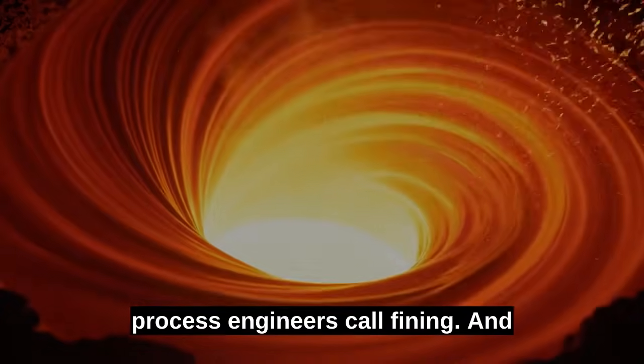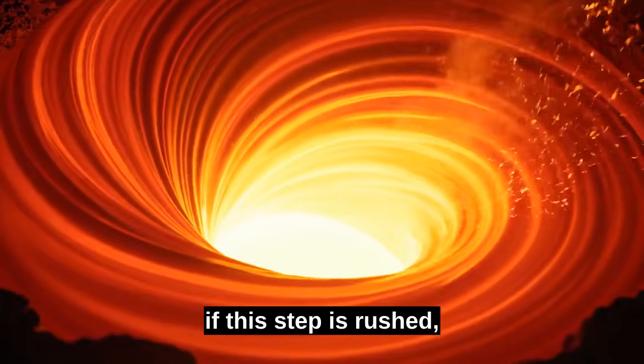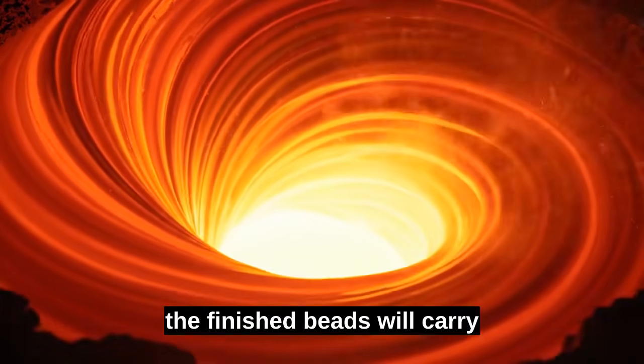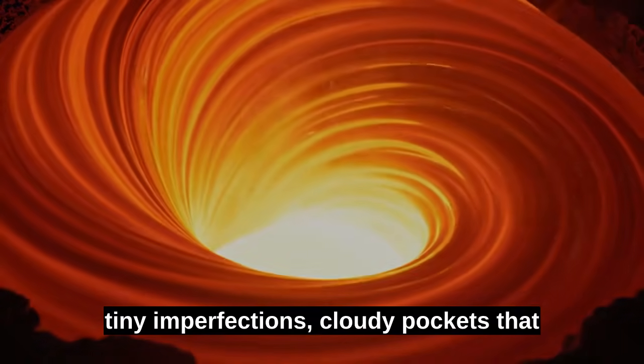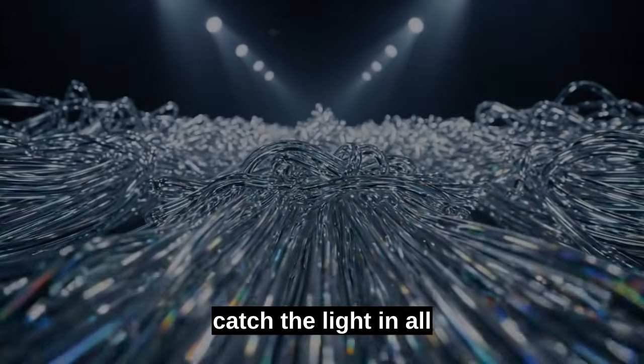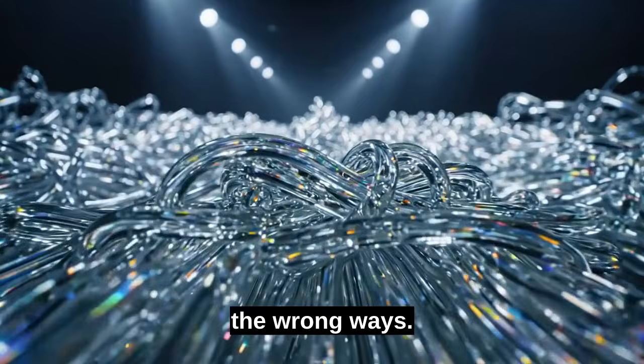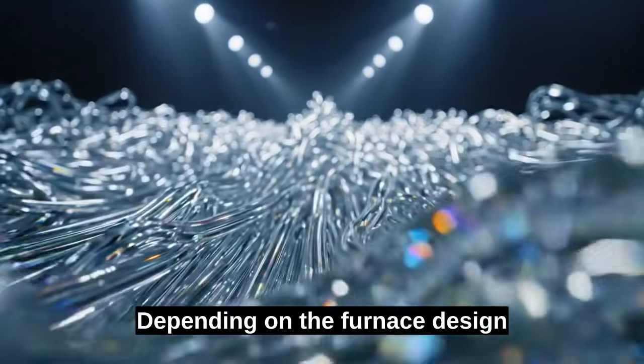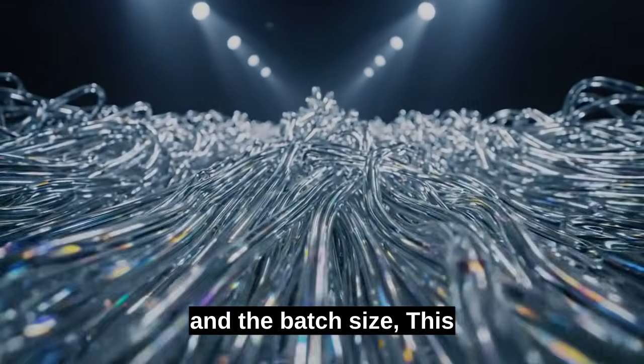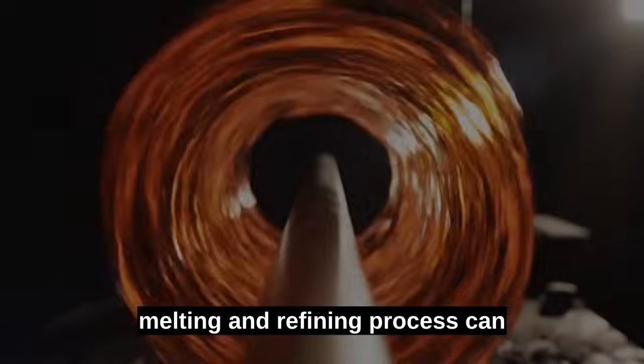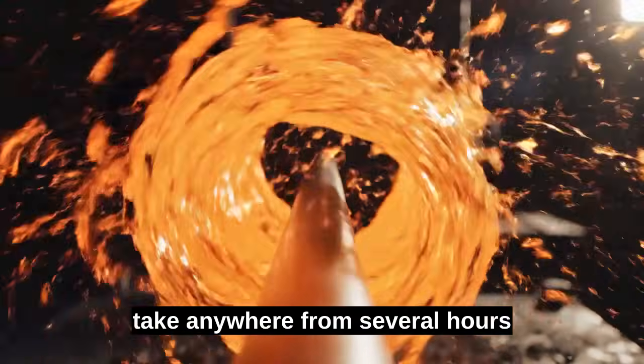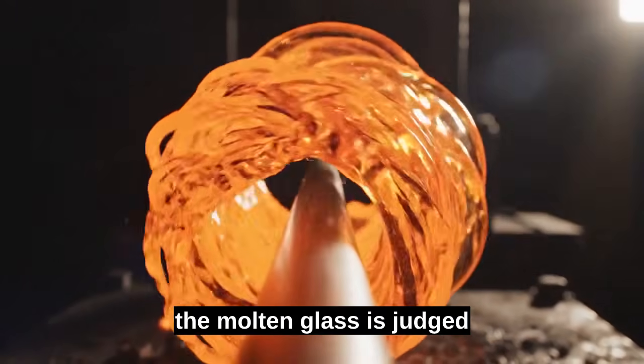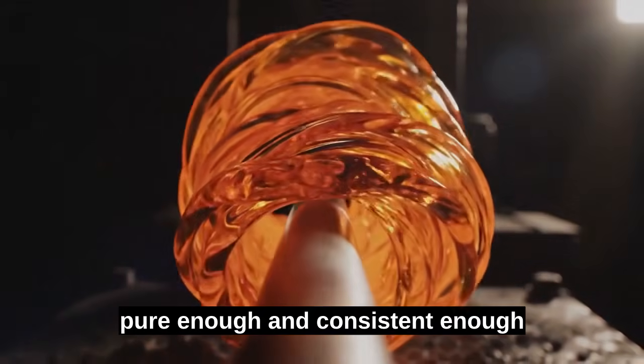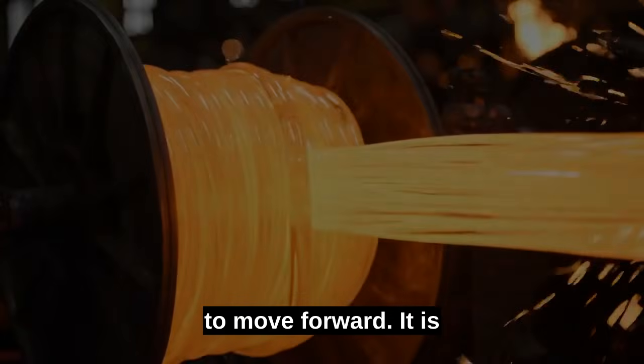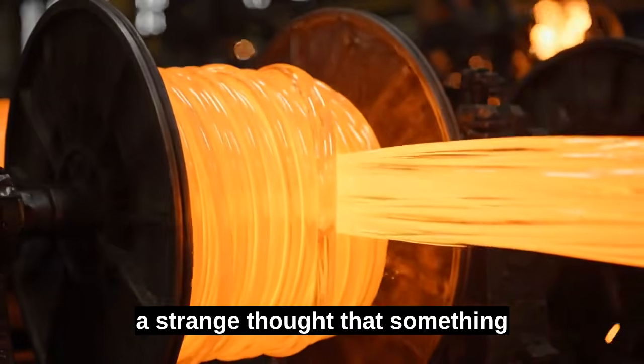As the raw materials melt, trapped air bubbles rise slowly to the surface in a process engineers call fining, and if this step is rushed, the finished beads will carry tiny imperfections, cloudy pockets that catch the light in all the wrong ways. Depending on the furnace design and the batch size, this melting and refining process can take anywhere from several hours to an entire day before the molten glass is judged pure enough and consistent enough to move forward.